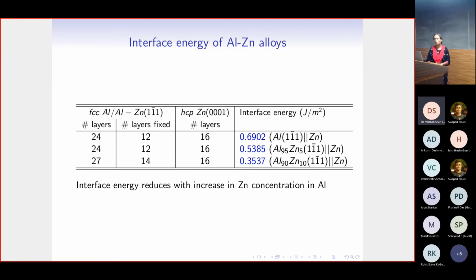Same procedure as we followed for the titanium, and now what we see is that if we increase the zinc dopant concentration, then the interface energy is reducing. Okay, so this, and I believe this agrees with what is experimentally observed. I don't have a very good experience working with aluminum zinc alloys. This is the first time I'm working with this, but I think this agrees with what I've seen experimentally as well.